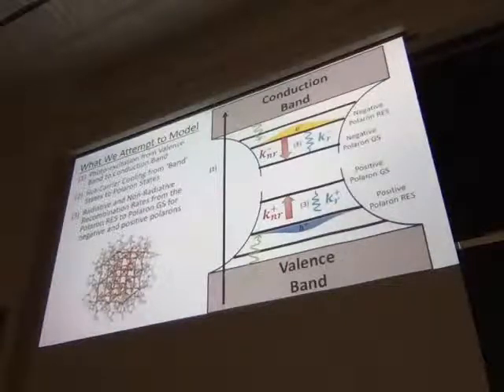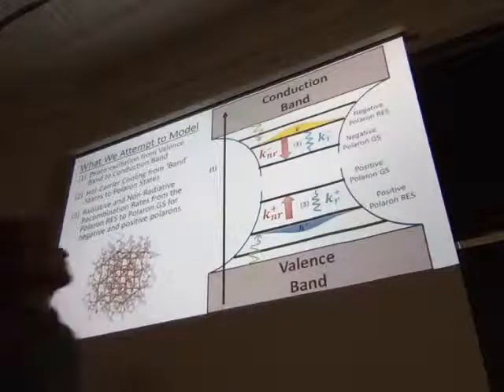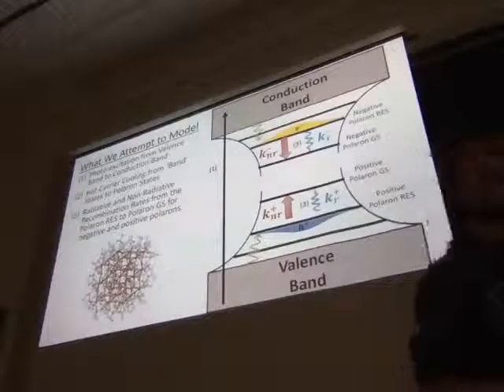Our atomistic model: we want to model a photo-excitation from the valence band to the conduction band, and monitor the carrier cooling to what's usually called, in the literature, the polaron relaxed excited states. You can have two different cases: an electron, or negative polaron, and a positive polaron. And then once they relax to these relaxed excited states, we want to determine the non-radiative rate of transitions between the relaxed excited states and the polaron ground states.